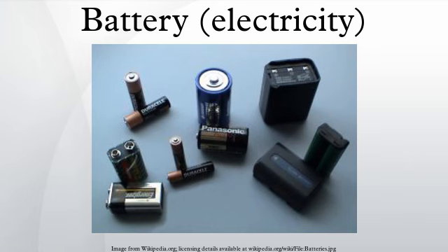Newer NiMH batteries are ready to be used when purchased, and have only 15% discharge in a year. Some deterioration occurs on each charge-discharge cycle. Degradation usually occurs because electrolyte migrates away from the electrodes or because active material detaches from the electrodes. Low-capacity NiMH batteries can be charged some 1,000 times, whereas high-capacity NiMH batteries last about 500 cycles.